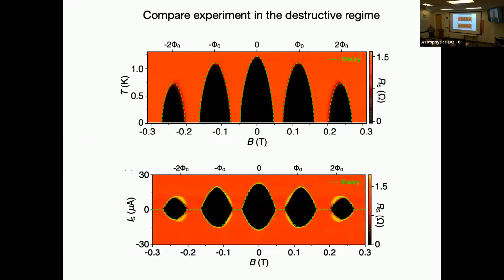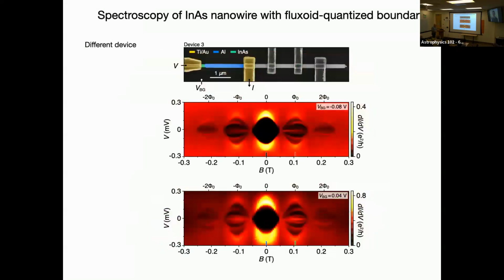And what's remarkable is how well it works. If you plug this into the destructive regime, you see there are the theory curves, both for critical current and critical temperature, and there's the experiment curve, one adjustable parameter for all of those lobes. The one adjustable parameter is that number right there, the critical temperature, or the critical current in forward and reverse directions. Everything falls out just from the geometry of the device and its normal state. It's just pretty remarkable agreement with the mean field theory.